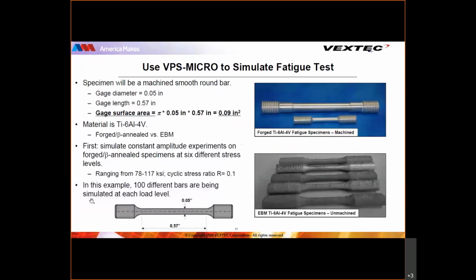Mike? Thanks, Bob. So before I show you the software, I'll set up this kind of example problem that we're going to look at. Here I'm showing examples of two different fatigue specimens. The upper image are specimens machined from a forged beta annealed Ti-6-4, and the lower image shows Ti-6-4 specimens produced via electron beam melting. The image here shows unmachined specimens, but we'll be simulating specimens that have been surface machined so that the roughness is reduced.